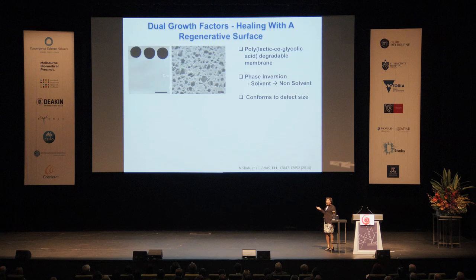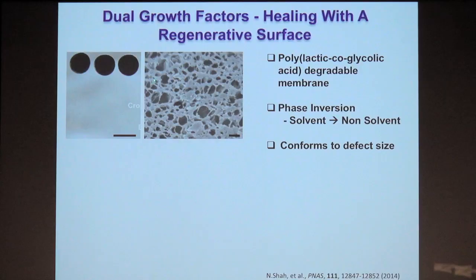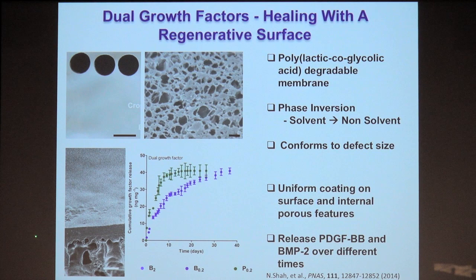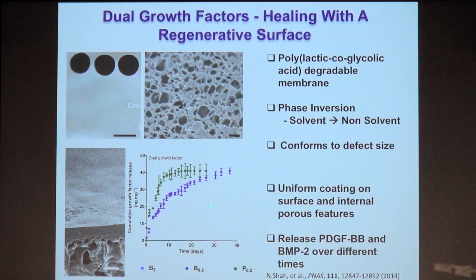So we take that polyester and we make a really porous version of it with a lot of holes in it. It's porous and flexible. We cut it into the size of the defect that we want to repair, and then we coat it with nanolayers. And the nanolayers that we put down include bottom layers that contain this bone morphogenetic growth factor, or BMP2, and top layers that contain PDGF. And remember, PDGF helps build blood vessels.